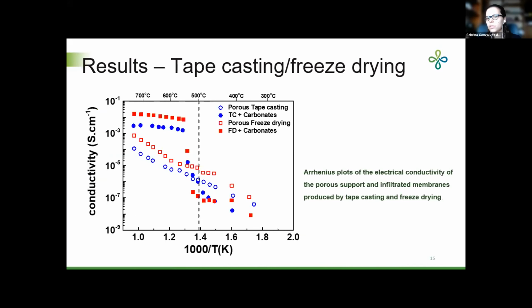So this is the Arrhenius plot of the electrical conductivity of those samples produced by tape cast in blue and freeze drying in red, with and without the carbonate infiltration. The behavior of these samples is similar to the results that I have already shown before. We have a linear trend for the samples without the carbonate and 3 different stages for the samples with carbonate infiltration. What is interesting to notice here is that the freeze-dried samples showed a higher conductivity for both porous support and infiltrated membranes because of their aligned pore structure and consequently lower tortuosity of the charge transport across the transport direction.